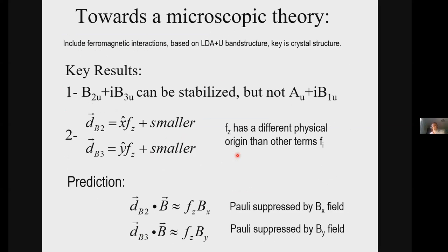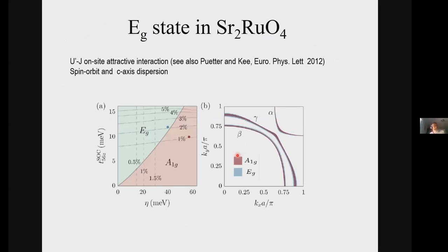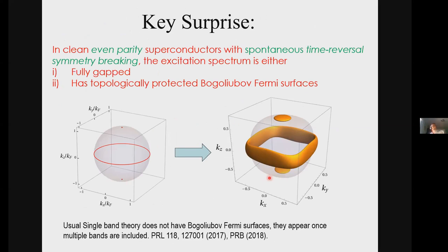Yes, you are right. And the fact that we have multiple orbital degrees of freedom. So I've given maybe a quick picture of what happens generically. This is not really strontium ruthenate, but here is the line node you're talking about, and this is a Kz, Kx plus iKy type order parameter, but in 3 dimensions that has point nodes up here and there.